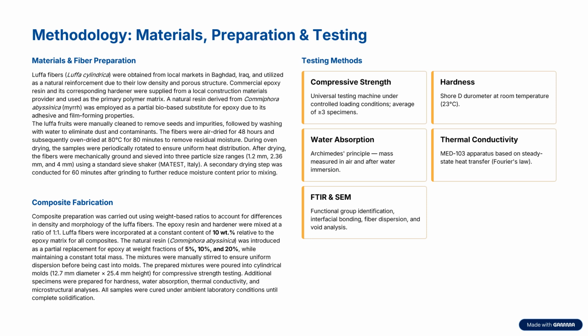For that, we prepared the composite using Luffa fibers, which were obtained from local markets in Baghdad and utilized as a natural reinforcement due to their low density and porous structure. Commercial epoxy resin and its corresponding hardener were supplied by a local construction material provider and used as the primary polymer matrix. Natural resin derived from Commiphora was employed as a partial bio-based substitute for epoxy due to its adhesive and film-forming properties.